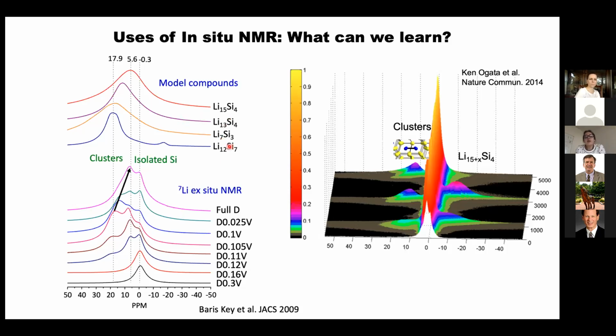And so the Li12Si7 and the Li7Si3 compound contain little clusters. And so this is one type of cluster where you get a silicon-silicon bond surrounded by lithium, and that gives you these peaks at about 18 to 20 ppm. And then when you have isolated silicon, so in this final compound, the Li15Si4, you get shifts at lower frequencies.